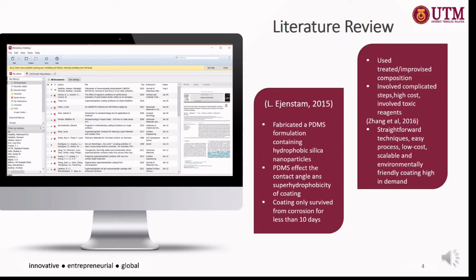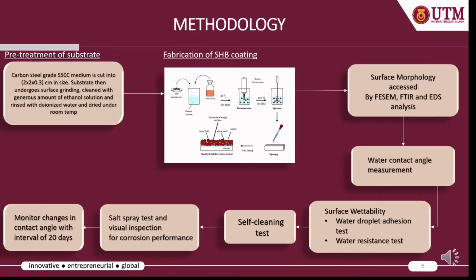anti-corrosive performance autonomously. The research methodology is as follows: firstly, carbon steel grade S50C medium is cut into 2 by 2 cm in size. The substrate then undergoes surface grinding, is cleaned with a generous amount of ethanol solution, rinsed with deionized water, and then dried at room temperature.